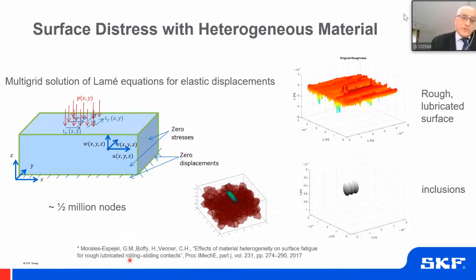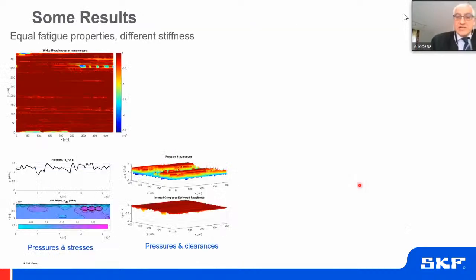So we have done that with the help of our colleagues in the University of Twente with Professor Kees Venner, where we can actually model in a simple PC computer up to 500,000 nodes or even more, depending on the modeling, if it is transient or steady state. And what we try to do here is to take a typical bearing topography. And then we introduce some inclusions made of a stiffer material than the matrix. And then let us investigate what happens with those.